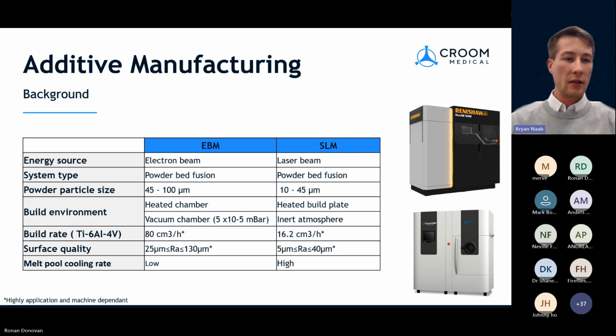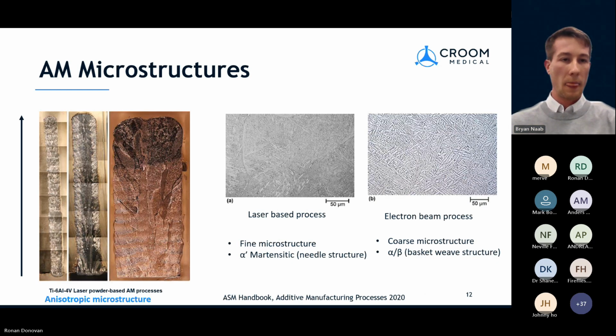Additionally, E-beam is a hot chamber process, so the cooling rate which is experienced by the molten metal will be low relative to SLM, which relieves residual stresses and coarsens the microstructure. Additionally, E-beam is conducted in a vacuum, while SLM is generally conducted in an inert atmosphere, such as argon gas.